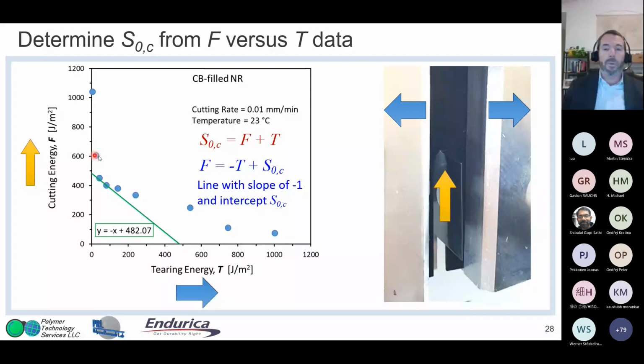You get some frictional contributions from the blade. If the crack's just barely open, you're pushing the blade in, there can be some friction. And then you do start to see some hysteresis contributions that can show up at high tearing energies. But you can see that there's a place where this behavior is minimized. And that's what basically was proposed by Lake and Thomas, is that you have your normal tearing energy, that's the blue, and you have the cutting force, which is coming from the blade, and there's this intrinsic cutting energy, S, that comes out of the measurement.